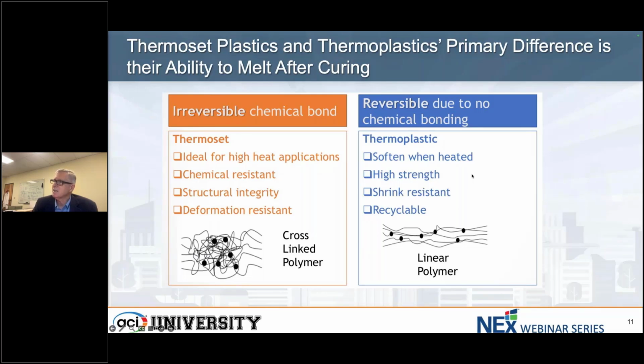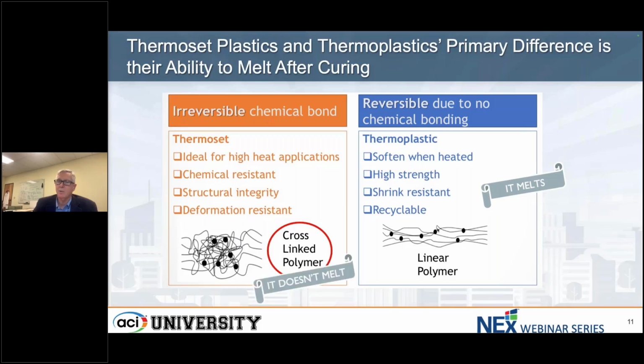A thermoplastic is a reversible type of cured polymer, and you still get basically a pseudo crosslink, but the kinds of things that form the pseudo crosslink, which are shown in the black dots here, are hydrogen bonds or things that can reverse with temperature. So they soften with heat. They can be high strength, they're shrink resistant, and they're a lot more easily recyclable, although we'll talk about that later. So the big difference between a thermoset and a thermoplastic is when you heat it up, a thermoplastic melts, but because you have an irreversible crosslink in a thermoset, when you heat it up, it doesn't melt. And if you keep heating it up, it just burns.